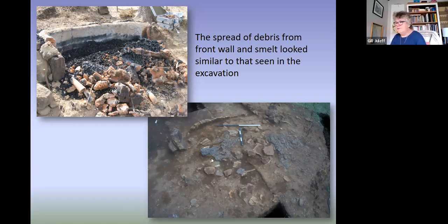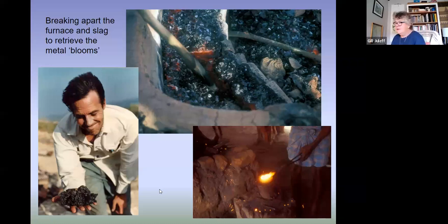Okay, so the big question is, what did we make in our furnace? And you can see here we're breaking up the slag at the bottom of the furnace, and out of that mess we retrieved several lumps of iron, what we might call iron blooms. Not very much. I would certainly not make it as an iron making magnate in the commercial world, but we did make iron, which we took to the local blacksmith, who at first was very skeptical that it contained metal, but we persuaded him, and he forged it very successfully into a small bar within a matter of less than 20 minutes.